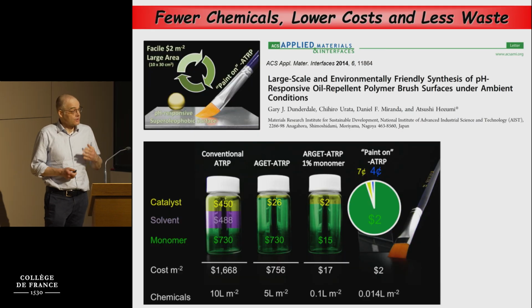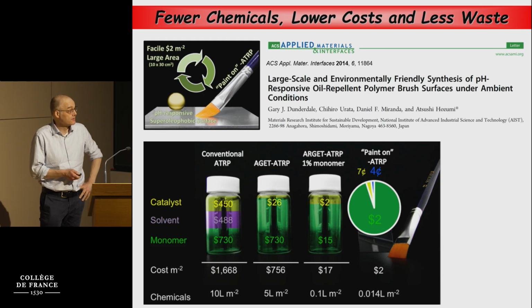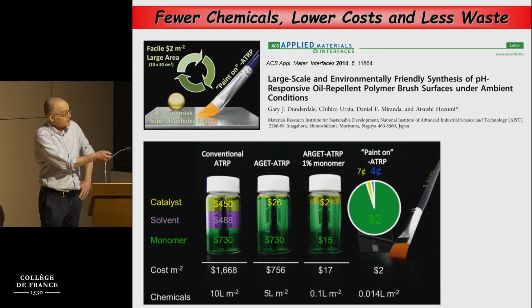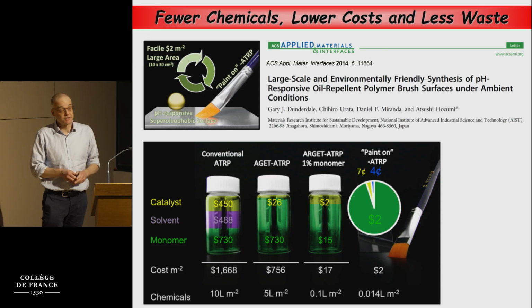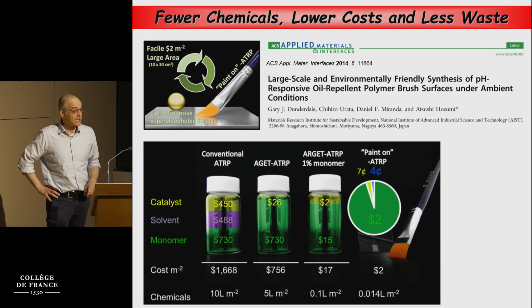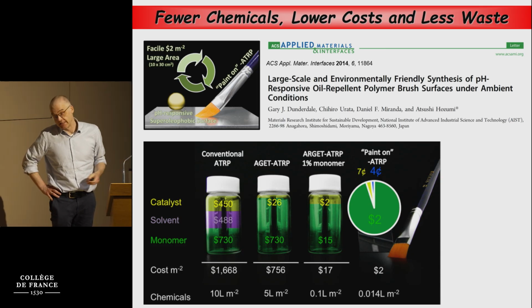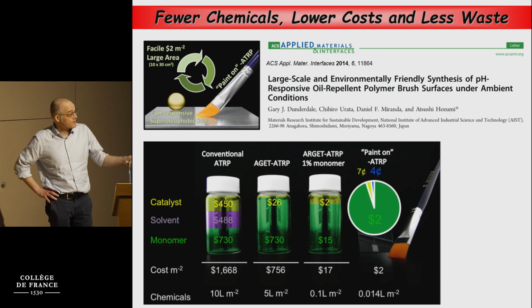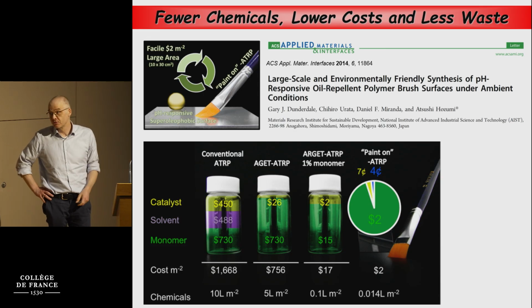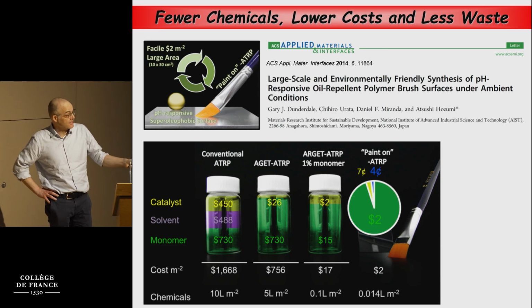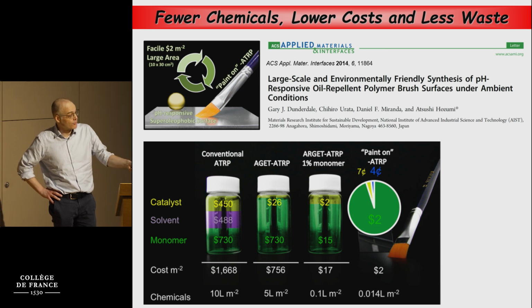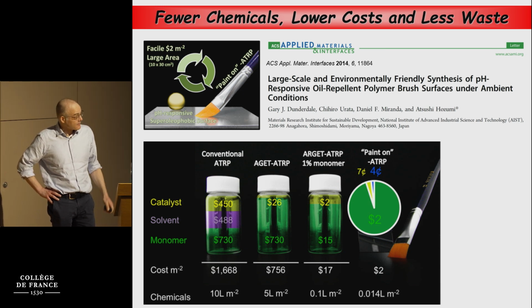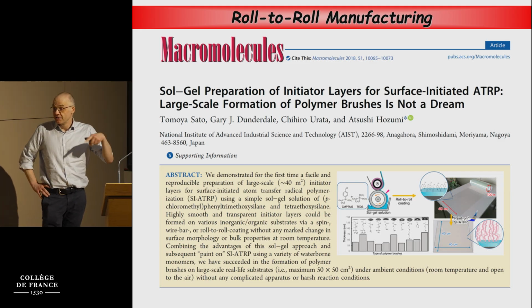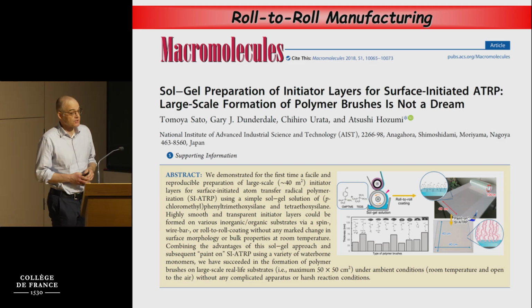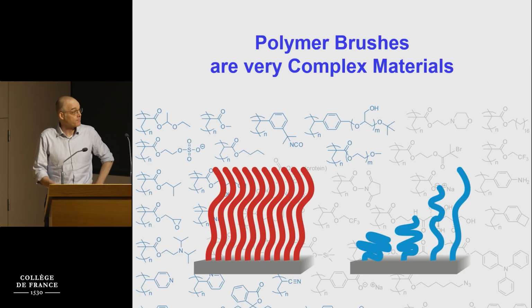Another interesting thing, if you look at the evolution of controlled radical polymerization methods, is illustrated here. That's basically the enormous decrease in cost per square meter if you think about surfaces, or chemicals per square meter if you think about surface-initiated polymerizations, which is actually due to all these refinements in catalytic methods. About 2 decades ago, a square meter of a brush would cost about $2,000 and would use about 10 liters of chemicals per square meter. Now we're down to 14 ml per square meter and about $2. And there are also nice examples where people show that you can actually integrate these chemistries with roll-to-roll processing and do things in a continuous way.